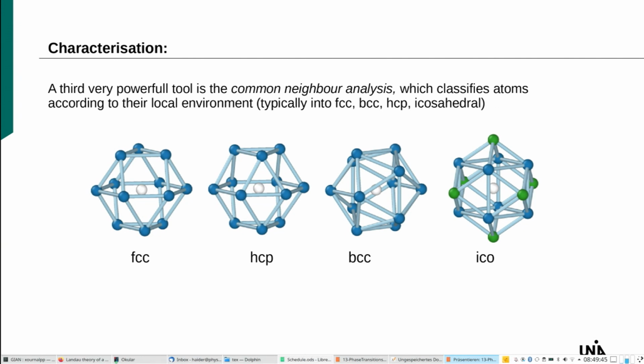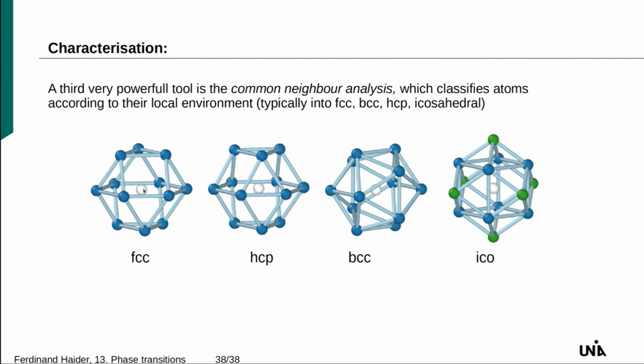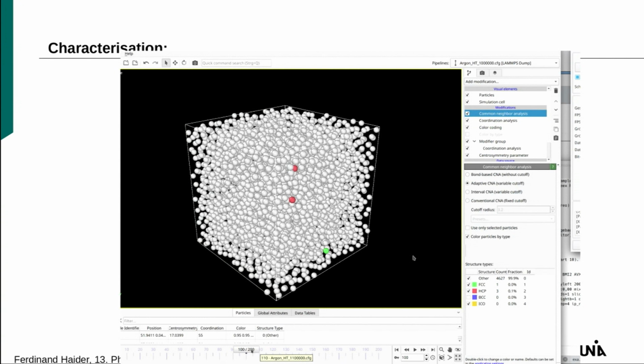Third one is a common neighbor analysis, which I think is what you used when you showed these stacking faults. It allows you to distinguish between different types of crystal structures - FCC, HCP, BCC, and icosahedric, for example. So you take the local environment and see whether it resembles an FCC structure, this dodecahedra, and the other structures here. And again, you can study this.